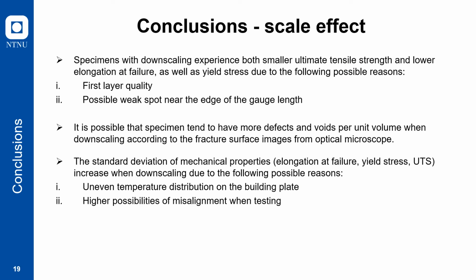So similarly, these are the conclusions for scale effects. First, specimens with downscaling experience smaller ultimate tensile strength and lower elongation at failure, as well as lower yield stress, due to a few possible reasons. First is the first layer quality. As we know, FDM printing is a technique where the first layer quality is very important to the overall printing quality, and it is influenced by so many other factors. That's why the first layer quality is one of the possible reasons to affect the scale effect.